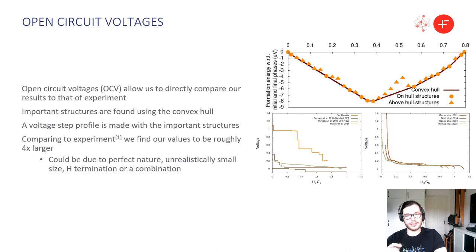One final particularly useful bit of analysis we can perform on our structures is finding the open circuit voltages. Now this is particularly useful because we can directly compare our results to that of experiment. In order to find an open circuit voltage using computational results we need to look at the convex hull to find the important structures.